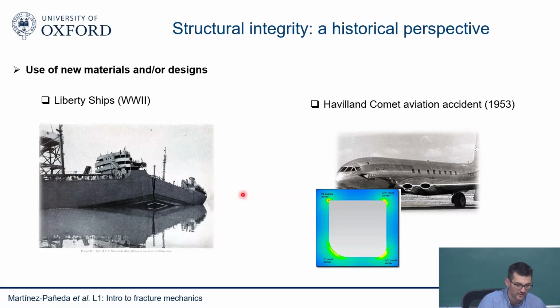I think they built almost 3,000 of the ships, and they saw cracking in 1,600 of them. So more than half of those ships underwent cracking, and 18 of them cracked in half, as you see here, with, of course, a big loss of lives and resources. And this happened due to a lack of understanding of how those welds would behave, some sort of brittle to ductile transition, and some hydrogen embrittlement too, when those ships were going through near the North Pole.